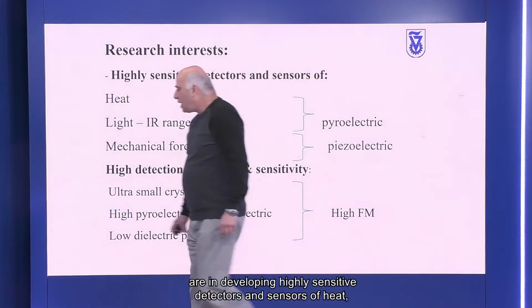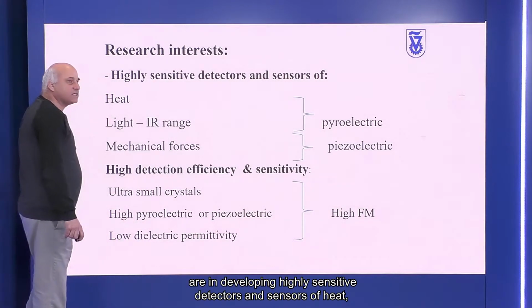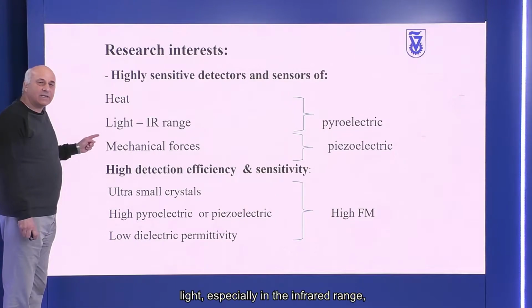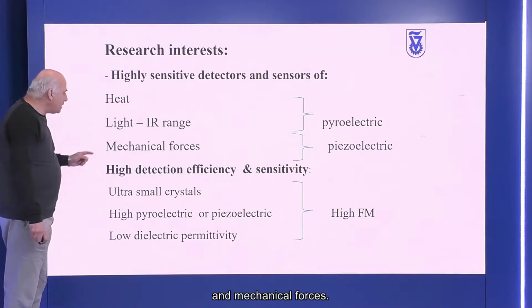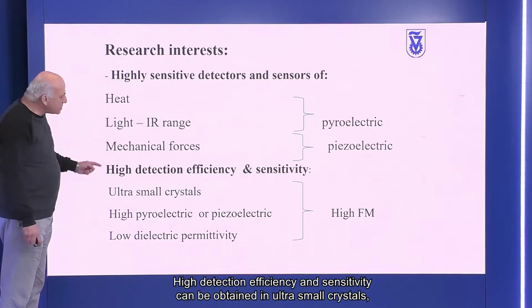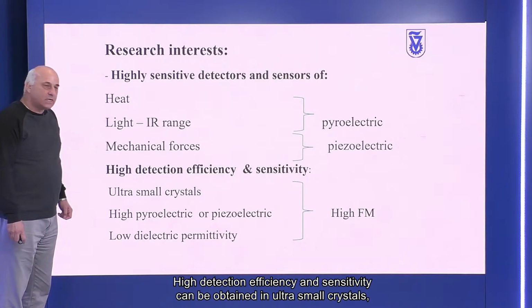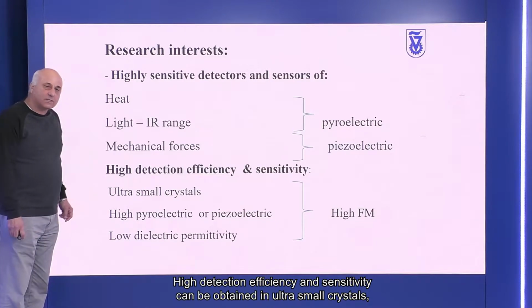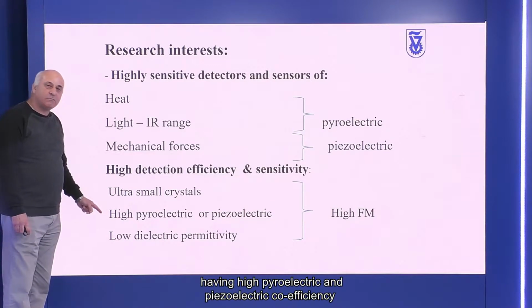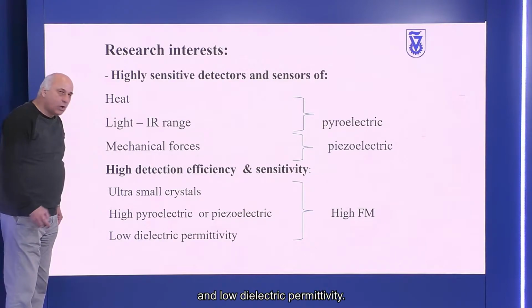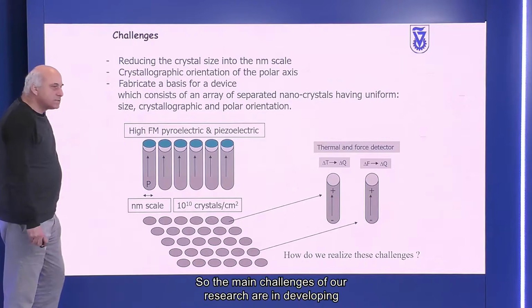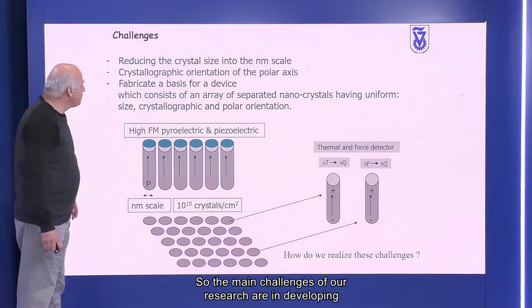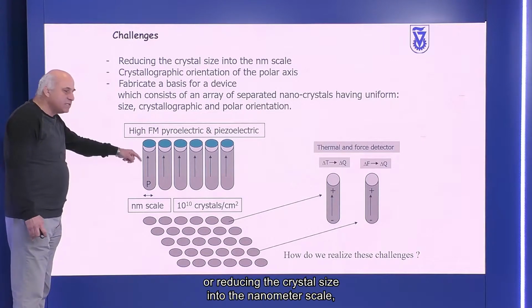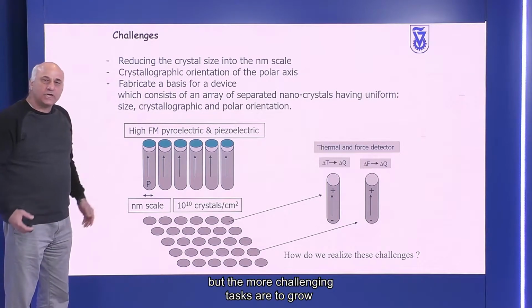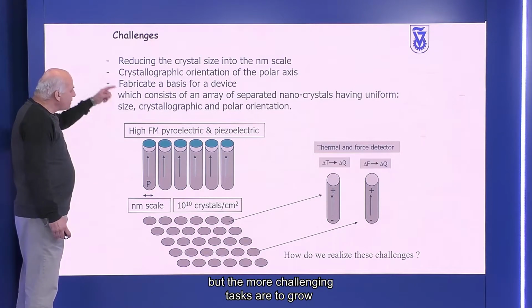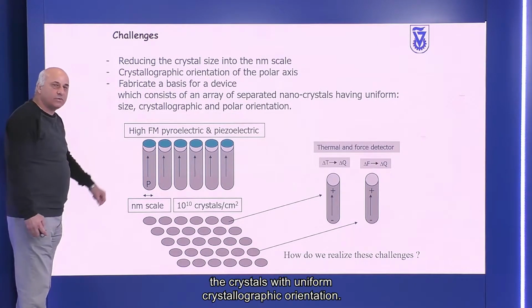Our research interests are in developing highly sensitive detectors and sensors of heat, light, especially in the infrared range, and mechanical forces. High detection efficiency and sensitivity can be obtained in ultra-small crystals having high pyroelectric and piezoelectric coefficients and low dielectric permittivity. So the main challenges of our research are in reducing the crystal size into the nanometer scale, but the more challenging task is to grow the crystals with uniform crystallographic orientation.